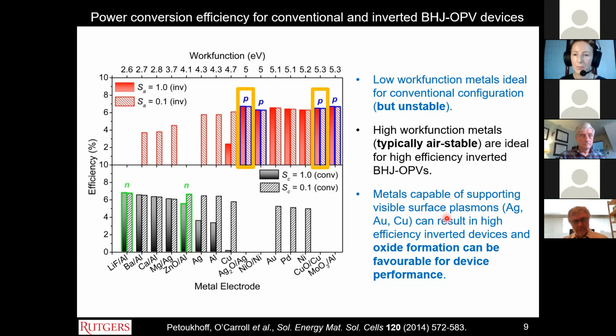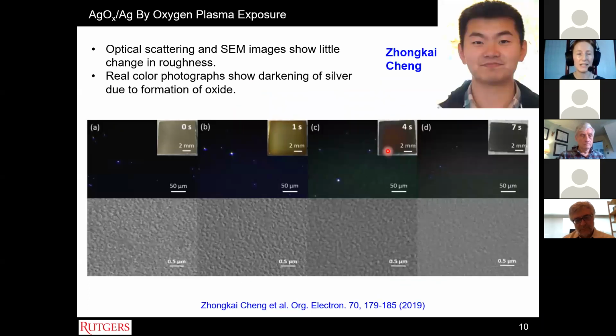Metals capable of supporting surface plasmons can therefore result in high efficiency inverted devices, and oxide formation can be favorable as well for the device performance in the case of silver oxide, for example, or copper oxide. They will actually aid in improving or maintaining the efficiency. So that motivated us then to look at silver oxides on silver as a way to improve and stabilize the performance of the inverted devices.